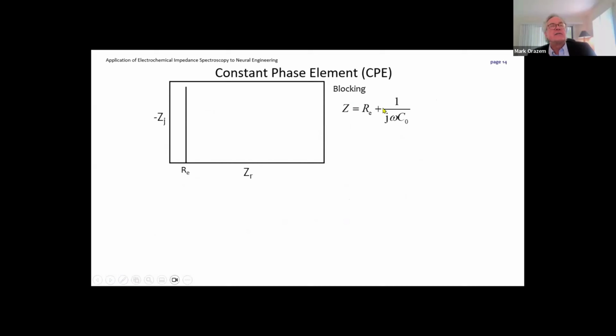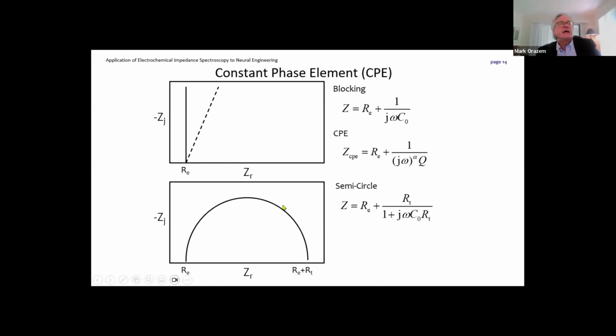So for example, if we have just an ohmic resistance in series with a capacitance, then we would see a vertical line in a Nyquist plot. But if we have a constant phase element, then this j omega, the imaginary number times frequency, is raised to an exponent alpha. And then we replace the C with a Q just to remind us that C and Q don't have the same units. So this is a constant phase element. If we have a charge transfer resistance, then the constant phase element basically gives rise to a depressed semicircle.